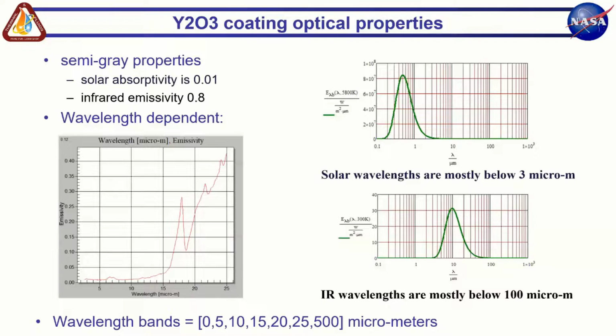And just on the right, I've plotted on a log chart what the solar energy is, at maybe 5800 K, compared to just a room temperature 300 K, and you can see where the peak wavelengths are. In the solar region, around 3 microns, it's pretty constant around 0.01 if you look at the actual chart. By the way, since I go out to 500, I assume it jumps up at 25 to 0.8 and is constant at 0.8 out to 500. I don't show that on the chart because if I did, you wouldn't be able to see anything.